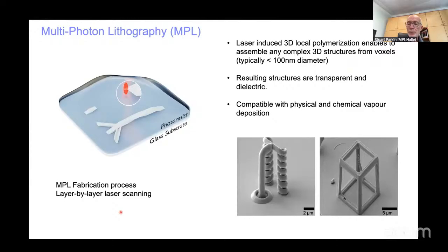We've also, this is another project of a PhD student, Andre Farina. He demonstrated the possibility of building using something called multiphoton lithography. This is basically, we have a very, very tiny beam of light, which is very, very intense. And we use that to photopolymerize a liquid polymer so that it forms a solid object. And this enables us to build scaffolds, as shown in the bottom cartoons, of almost any shape with a voxel size. The smallest size possible is 50 nanometers. And so these 50 nanometer voxel sizes are several times smaller than any commercially available printing device.